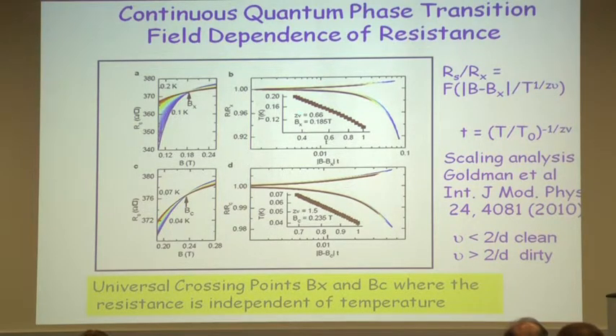And one can do a scaling analysis. We have followed the approach of Alan Goldman in describing the continuous quantum phase transition in two-dimensional superconductors. One can extract the critical exponents, and it's very clear that we have two continuous quantum phase transitions in the system. Now one would like to ask, why two? Why not only one? And we have an explanation for that, and that comes from the two-carrier model, which I described in the beginning.